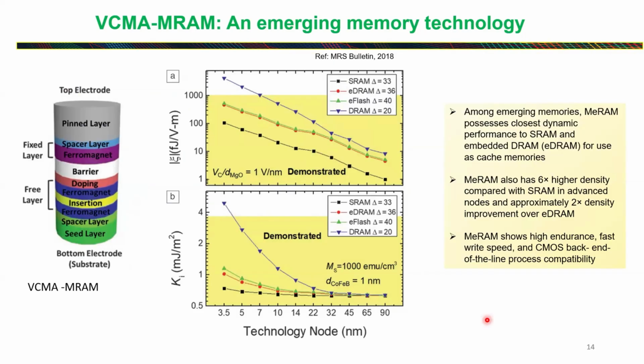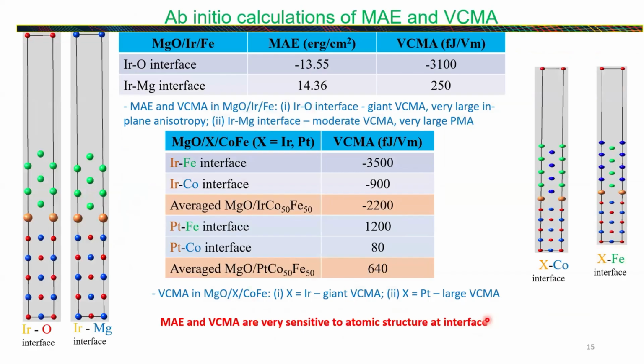So eventually, you need a higher VCMA coefficient, especially more than 100 femtojoule per volt-meter, to make something work at the lower technology node side. Okay, so we have done some ab initio calculations, and we found that when you introduce a thin layer of heavy metals like iridium, platinum, and others at the interface between the cobalt-iron-boron and MgO, you can modify the interfacial anisotropy. In fact, you can increase the PMA and even VCMA as well. And this is what we have done some experiments on.